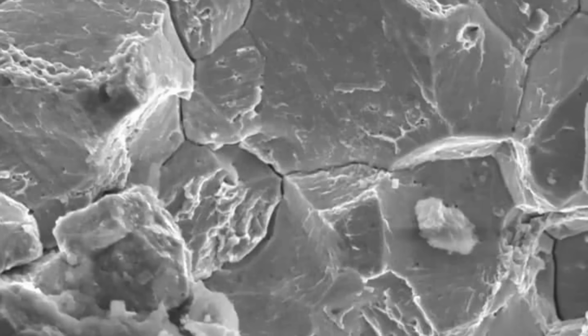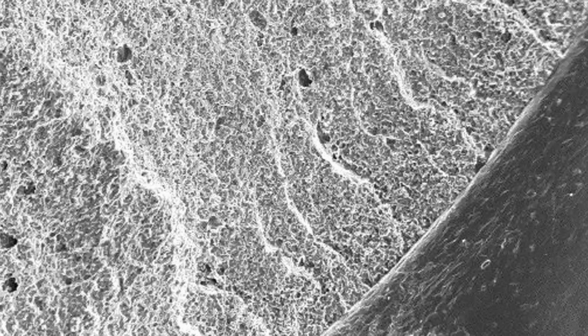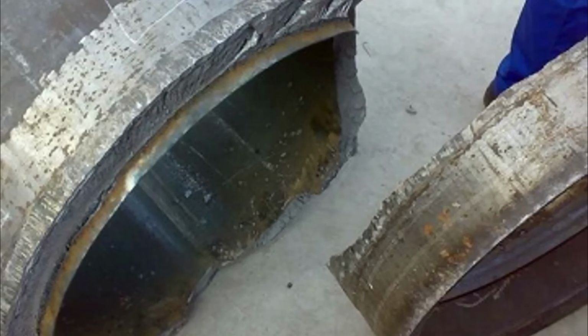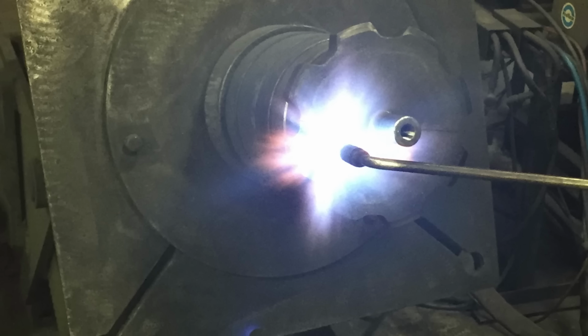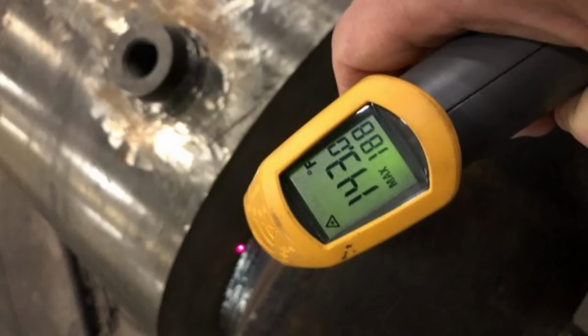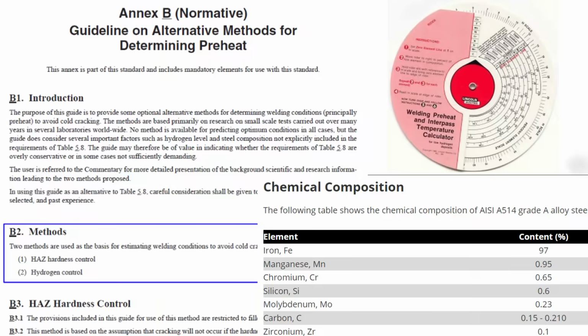When you weld, hydrogen can get trapped in the molten metal. If the weld cools too quickly, this hydrogen cannot escape before solidification, leading to cracks that can propagate over time and cause weld failure. Preheating slows down the cooling rate, giving trapped hydrogen time to diffuse out of the weld. Maintaining a minimum interpass temperature ensures that subsequent weld passes don't cool too rapidly. Engineers specify these temperatures based on material thickness, chemistry, and joint restraint to ensure the weld's integrity.